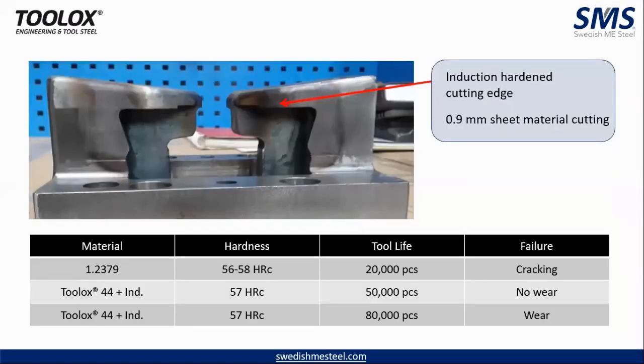And another cutting example, an induction hardened cutting edge. The sheet being cut was 0.9 mm material. Here, as you can see, the initial component was D2 at 56 to 58 HRC, with a tool life of 20,000 shots. The failure mode was cracking.